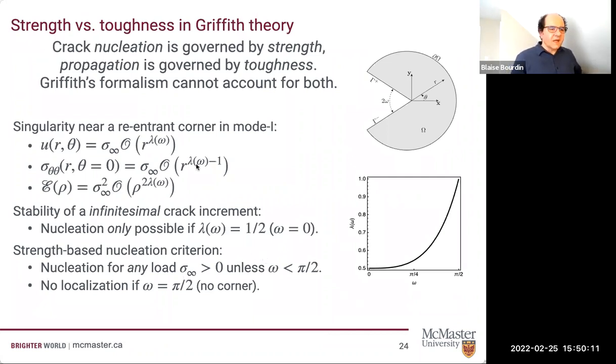Okay, I'm just going to say a few words about open problems, and one of the challenges is nucleation. The issue is that propagation is governed by the toughness parameter, the GC. That's a given. But Griffith's theory is really incompatible with the idea of nucleation, in particular with the idea of nucleation being governed by something called a strength. If you go to the Home Depot and buy some wire or some cable, you will get a limit load that is given in pounds or metric equivalent. Essentially, it tells you the maximum stress that your material can sustain before it breaks.